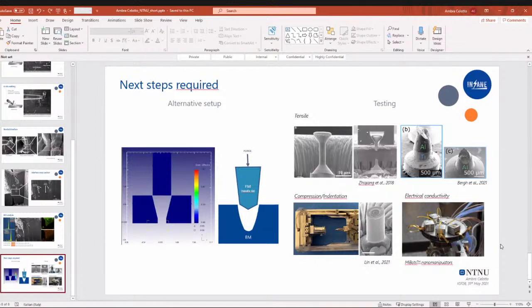Here I showed just the method for welding two aluminum alloys, but the main objective of the project is to try to weld at the solid state, at the micro scale, aluminum and copper, which are expected to form intermetallic compounds. And thus, there, the TEM analysis will be very useful to understand how this bonding mechanism occurs and which are the intermetallic compounds that are formed. And so basically understanding the bonding mechanism, in overall. Yes, understood. Thank you. Thank you very much.